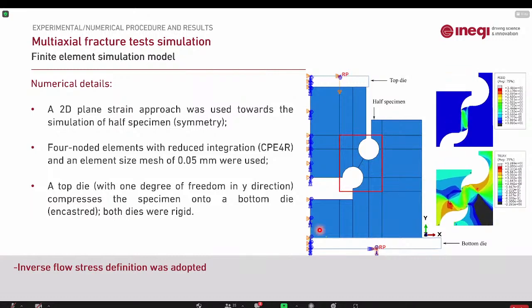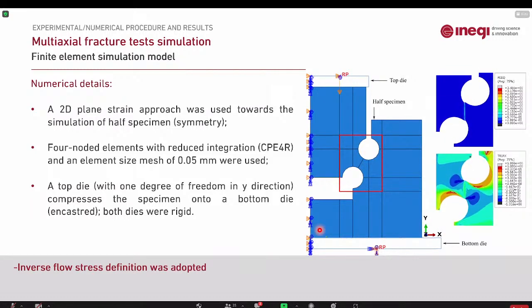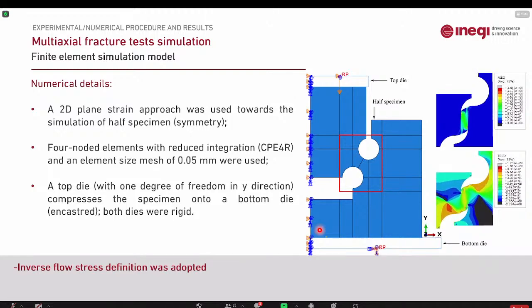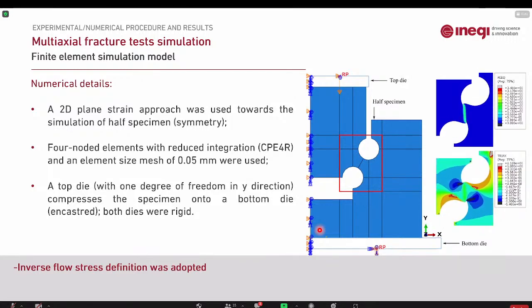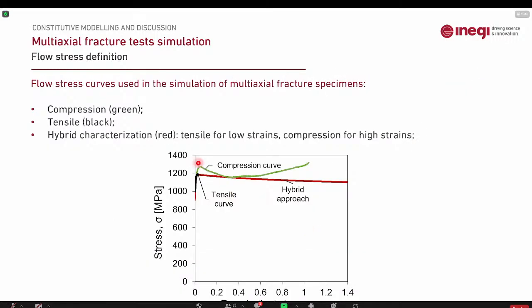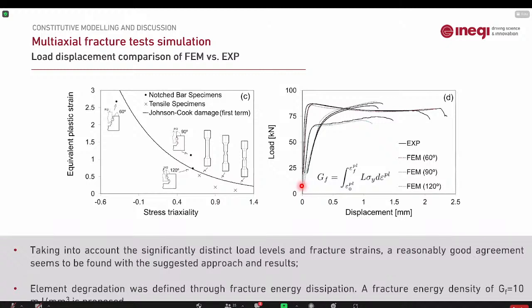Once again, the fracture strains and the flow stress curve were determined through numerical inverse analysis. Due to the slight differences between the compression curve and the tensile curve, we determined a flow stress through a hybrid approach that was compliant with both tests, as upper and lower boundaries for the hybrid approach. The tests also enabled us to determine the damage law.